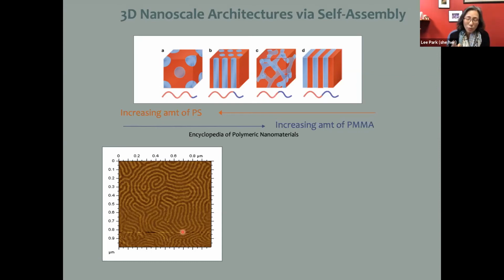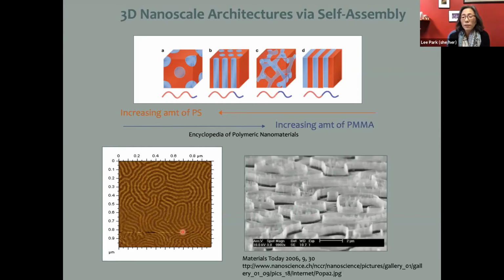That is, you can design your polymers such that you can take advantage of other properties that these materials might have. So for instance, they might be different in terms of solubility. So here is an image where somebody has created a film that looks like this and then dissolved away one of the polymers and left behind the other. And so you can see that what you're now creating is an architecture where, so this scale bar here is 2 microns, right? So this whole thing might be, let's say, 10 or 15 microns. So these walls are maybe tens of nanometers in height, okay? And so you're creating this nanoscale architecture where you've now built this network of walls.